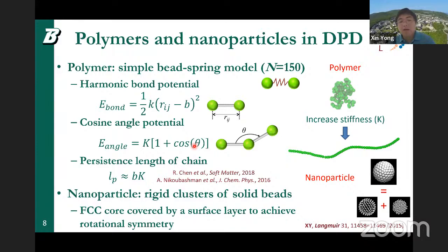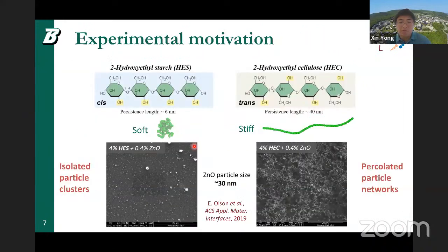In terms of physical units, for this particular problem, I can't recall whether we mapped it to physical units. We probably didn't. So I'll speak of the experimental system we're talking about. The particles are 30 nanometer. In the real experiments, I think we did characterize the size of the polymer, but I can't recall it off the top of my mind. The persistent length of the HEC is 40. The polymer itself is much longer for sure. But I believe we pick the ratio of the persistent length to the particle size to guide us in picking the particle size in the simulation. That ratio is the one that we really change.